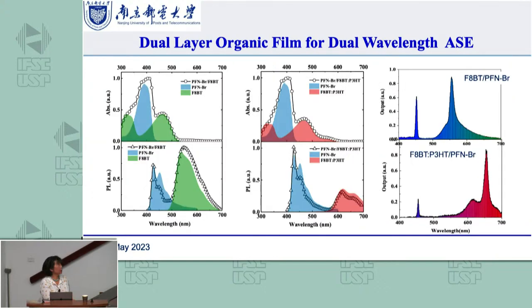Another way to test it is that we compared the monolayer absorption and PL spectra with those of the two-layer system, for red and blue and for green and blue. The monolayer and the two-layer spectra are a reasonable match. That means our two-layer system really works as two layers, and the second layer didn't destroy the first layer.